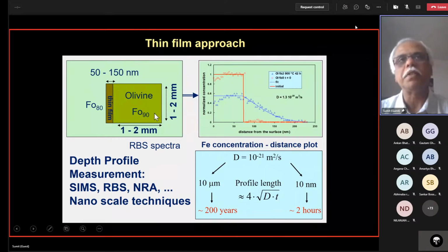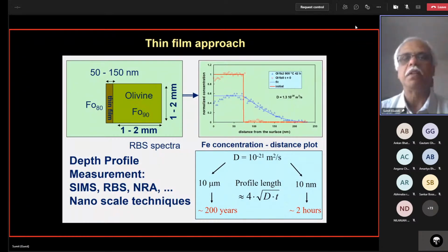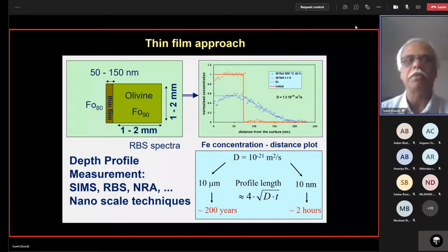So the olivine crystals, for example, mantle olivine forsterite 90, we take cubes about 1 to 2 millimeters in size, and then we deposit a thin film on that of only a few hundred nanometers in size. And the whole thing works because of two things that have happened in the last 20 or 30 years. We can manipulate material on the nanometer scale, we can deposit such things, and we can measure them. We can measure concentration gradients using a variety of techniques. For example, secondary ion mass spectrometry depth profiling, or we use things in an accelerator, very commonly in Bochum, which is RBS, Rutherford backscattering spectroscopy, or NRA, which is nuclear reaction analysis, and so forth.